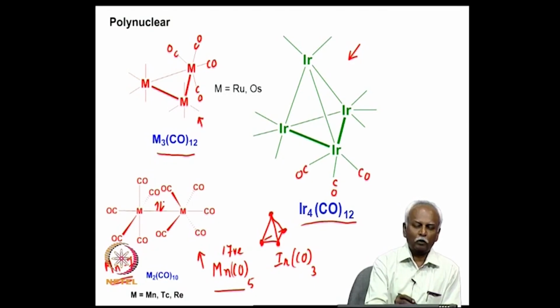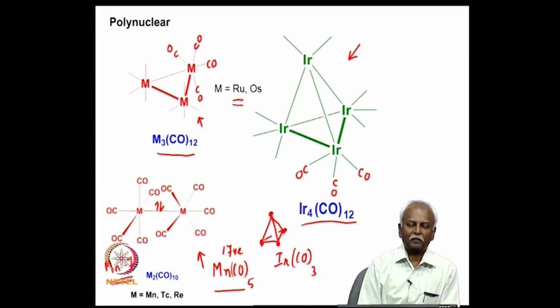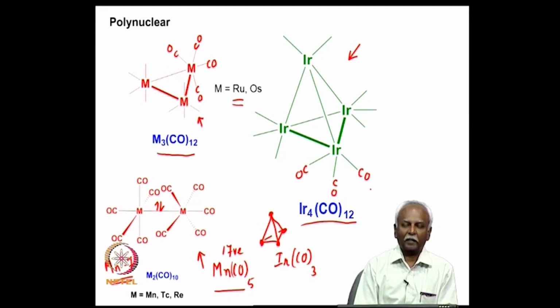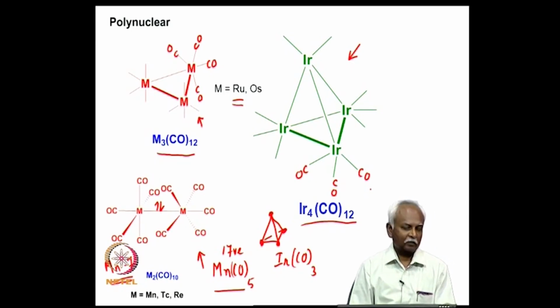Either it forms 2 bonds, as in the case of ruthenium, it has to form 2 bonds in order to achieve a valence electron count of 18, and in the case of iridium, it has to form 3 bonds in order to achieve a valence electron count of 18. So, the formation of a polynuclear species with a metal-metal bond is primarily determined by the electron count. This again brings us back to what we discussed earlier, and that is the fact that these metal complexes are significantly driven by the tendency to form 18 electron species. A total valence electron count has to be 18.